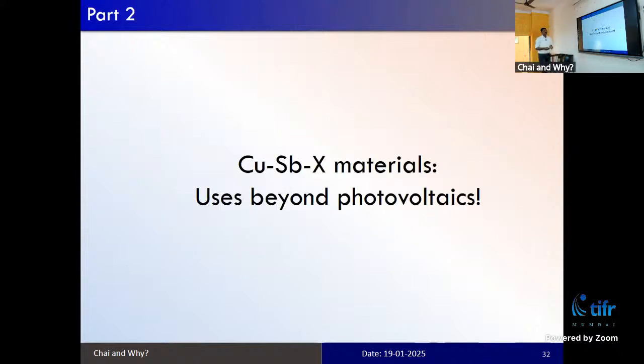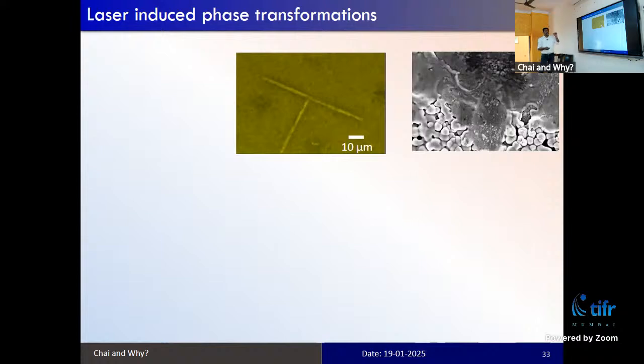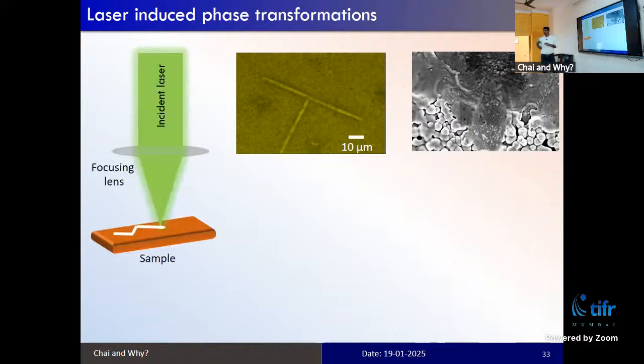Beyond photovoltaics, we have also studied what else this material can be used for. We observed a weird phenomenon: if you shine an intense laser light onto this copper antimony sulfide material, we see some marks, and there is laser heating or something happening in the substrate. When we were doing our Raman measurements, we found that if you increase the power of the laser, the material is transforming into something else. We wanted to analyze what is happening in the material using Raman spectroscopy itself.